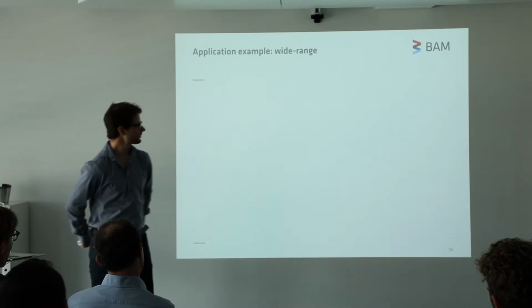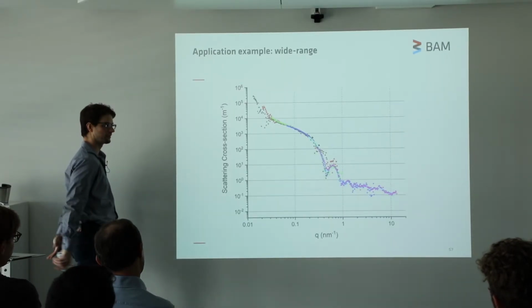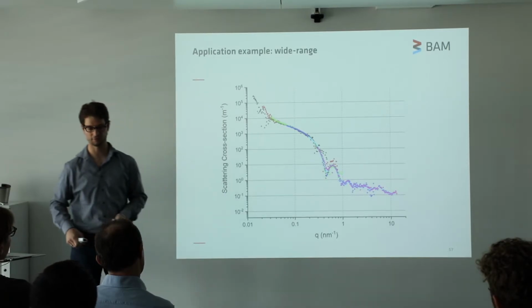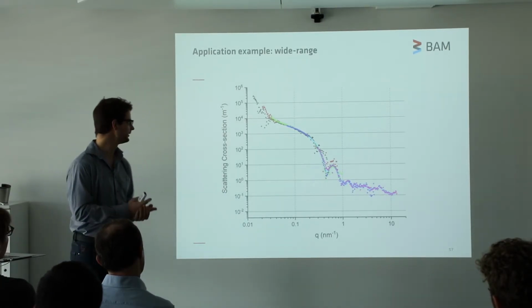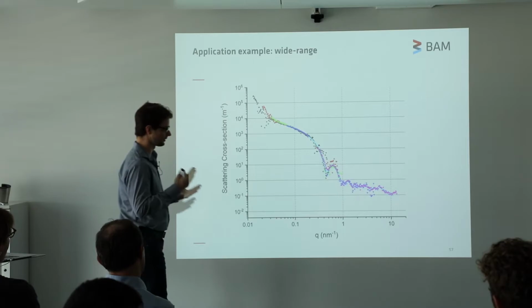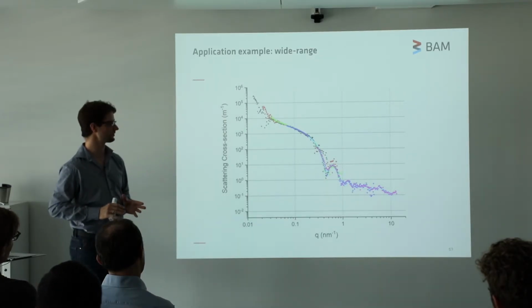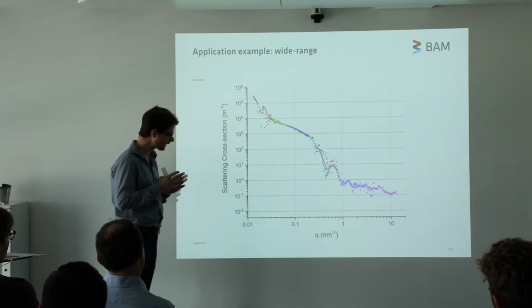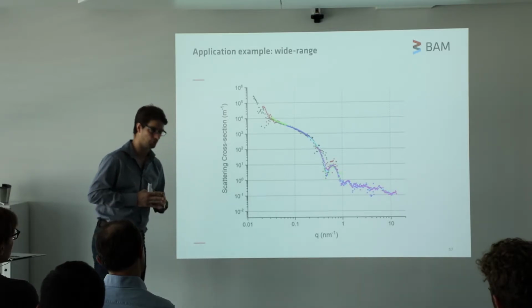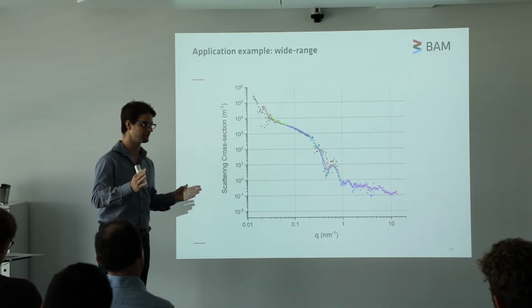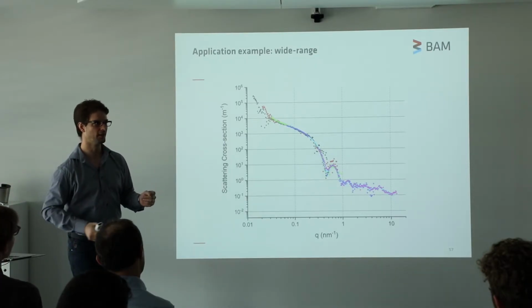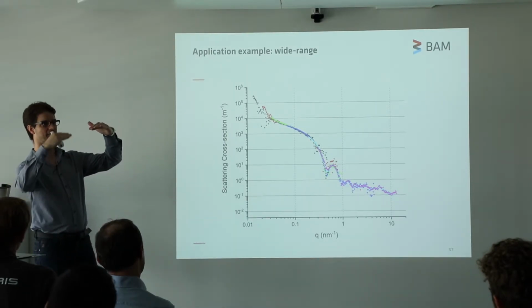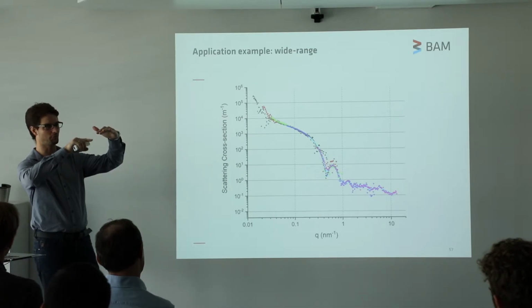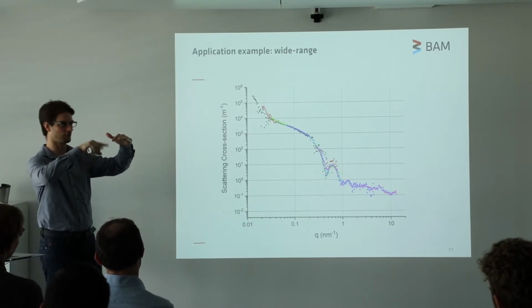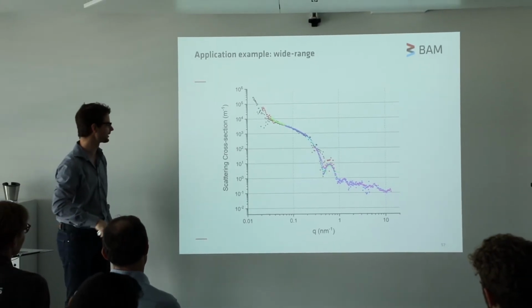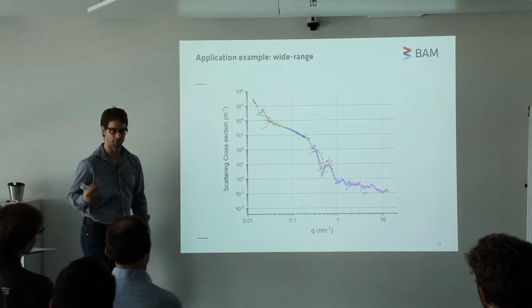Wide range examples are also some of our favorites. So as I said, we can move our detector at different positions in our camera. And this is done in a motorized way, so we can easily do 6 positions without breaking a sweat. And what you'd normally do in these experiments, if you have multiple detectors or if you move your detector around, is you take your two data sets, you find a scaling factor, and then you decide on a point where one data set is not good enough anymore and the other one should start. We don't have to do this anymore.